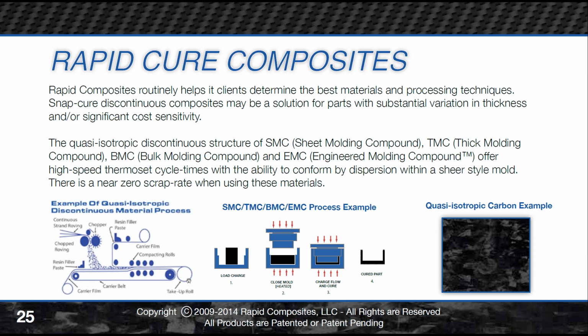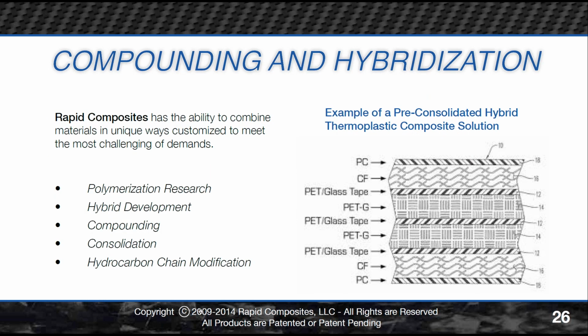Another thing that we do a lot of is compounding and hybridization. So this is an example of actually a patented version of a material. Well, it's actually a combination of materials here. We've got polycarbonate on the outside surfaces, carbon fiber. There's PET, polyester thermoplastic glass tape that's pre-impregnated unidirectional glass tape. And then there's PETG, which is polyester thermoplastic with glycol, that actually flows like water. And there's some significant things that are occurring in this compound solution that we have here, this hybrid pre-consolidated panel. Basically, we're creating a pressure intensifier with a sacrificial material, which happens to be PETG in this case. All of these materials are reasonably compatible in the form that we're putting them in. And it creates pressure intensification from the inside out.